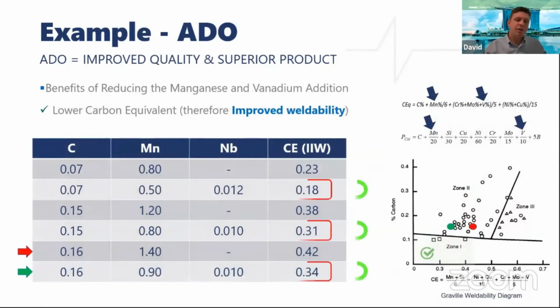On the weldability of the final product, you also have an improvement, because as you could manage to reduce the manganese, your carbon equivalent is lower, which leads to an improvement of the weldability of the same steel with the same level.